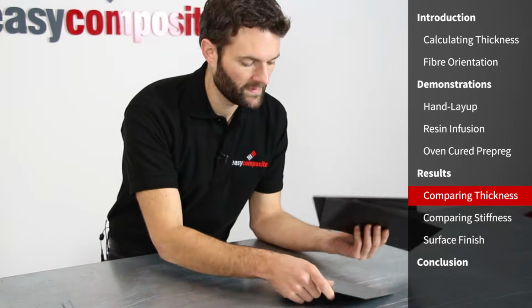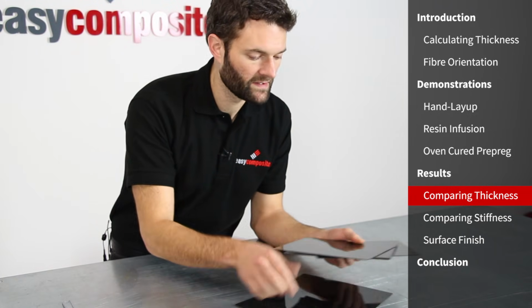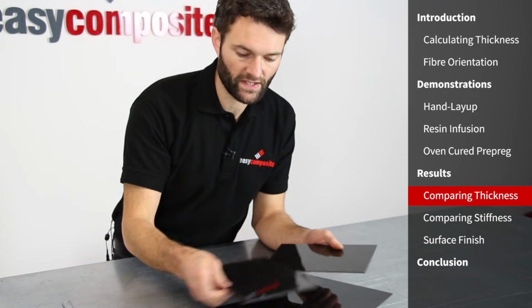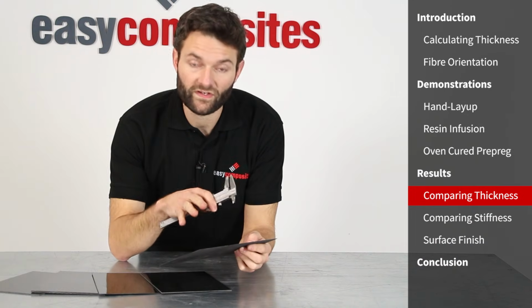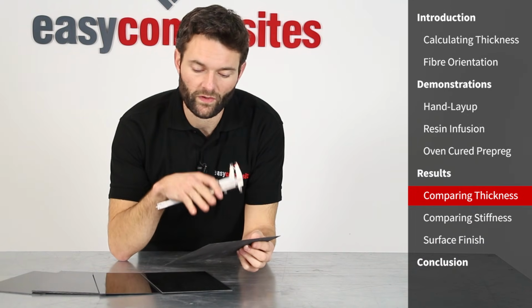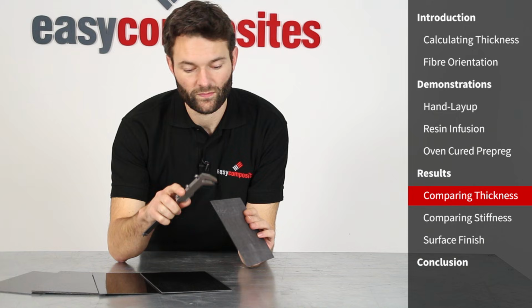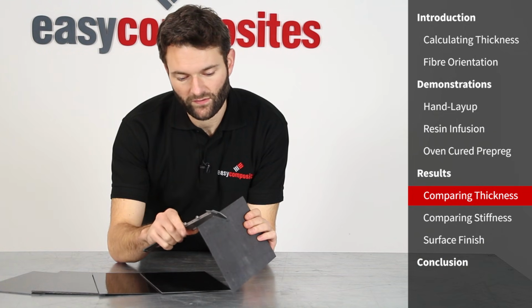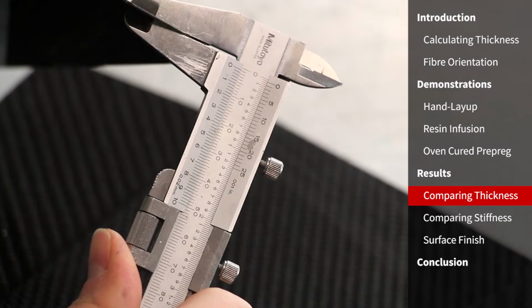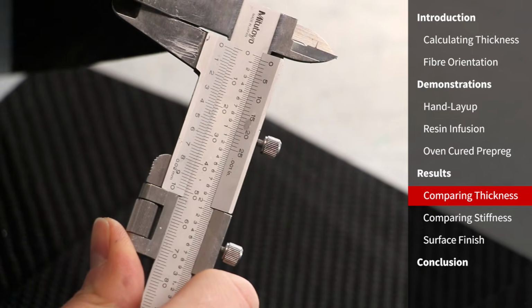The first thing we'll do is have a look at how the number of layers affected the finished thickness of these sheets. From the start of the tutorial, the first sheet that we made was the unidirectional, which we did as a wet lay process. And if we have a look at the thickness of that, we've got around about 0.9 millimeters on that one.